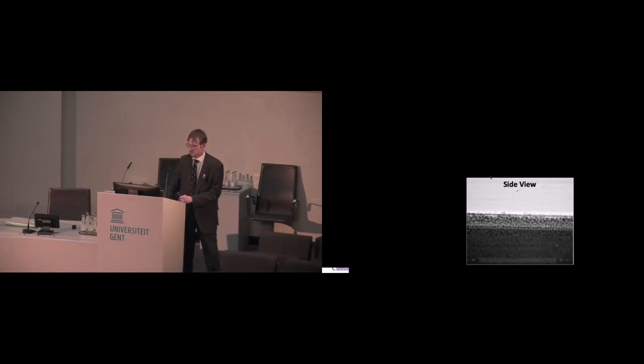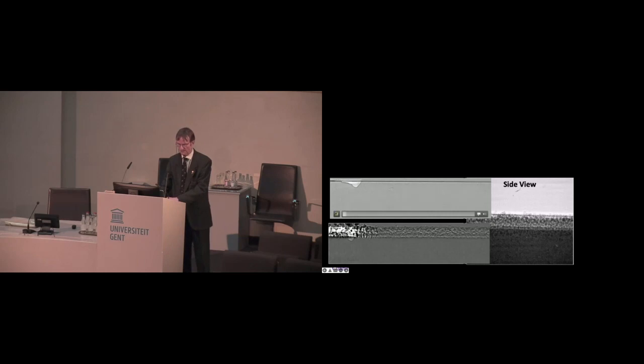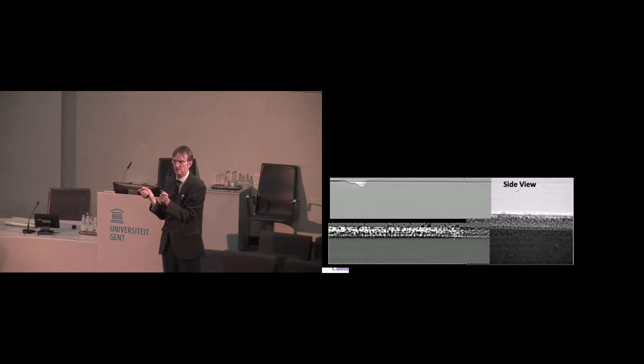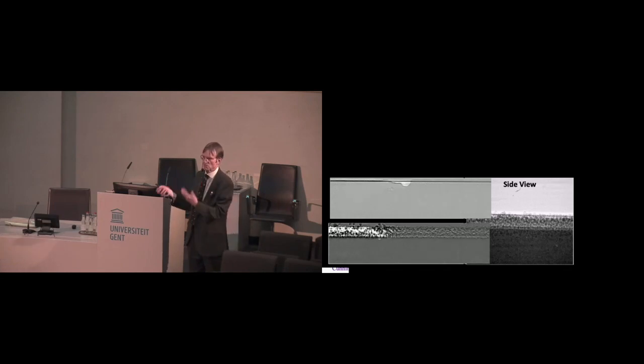And that's very, very important because what you then have to worry about is under what circumstances does this keyhole go unstable? And you can see that if you go quite a bit faster than was shown in that particular example, the keyhole stretches out. It's still there. There's still a vapor hole. There's still vaporization occurring. But it's much more shallow, and it's not going unstable. And so the other point here is that under most circumstances in most laser powder bed machines, there is a keyhole, but it is not necessarily an unstable keyhole. So we learned a lot about that.